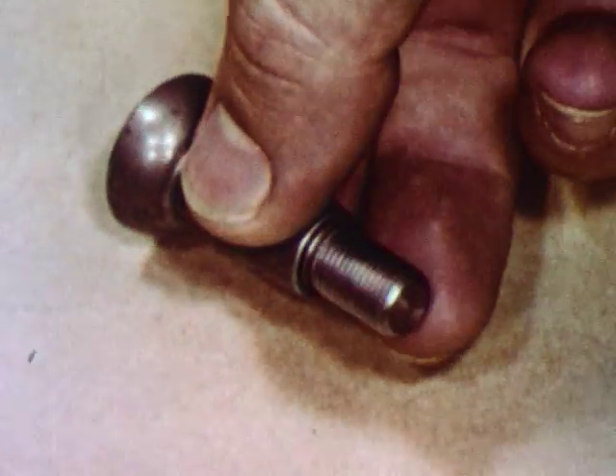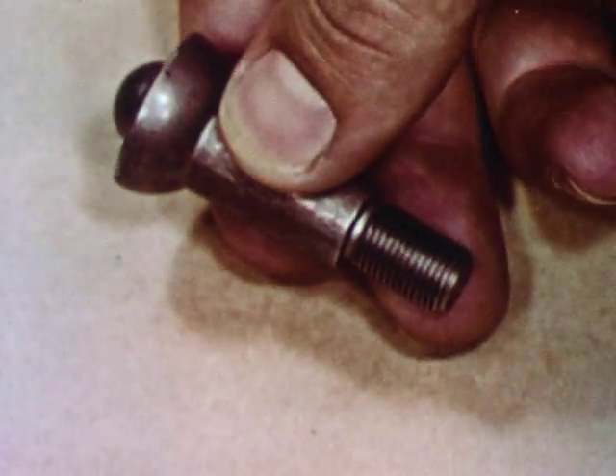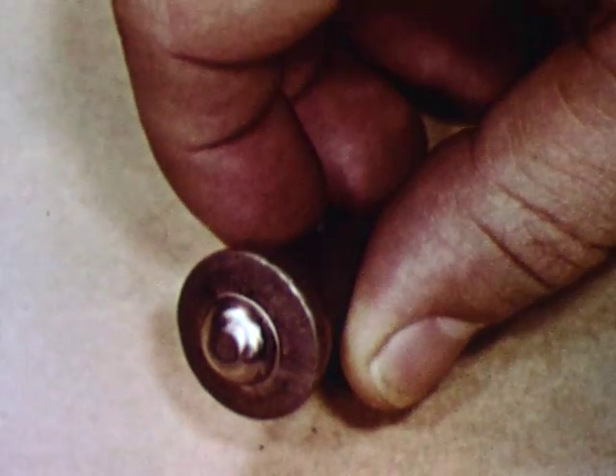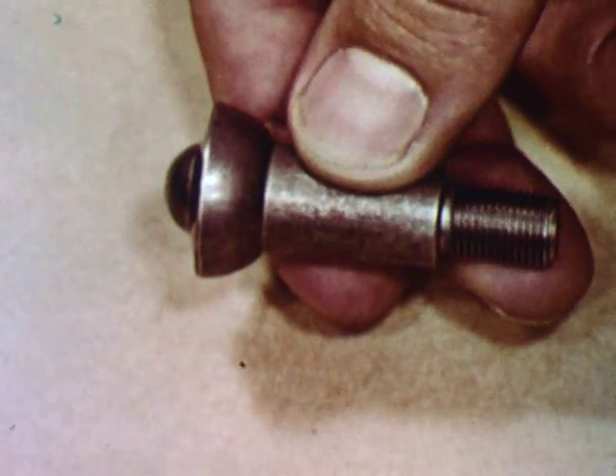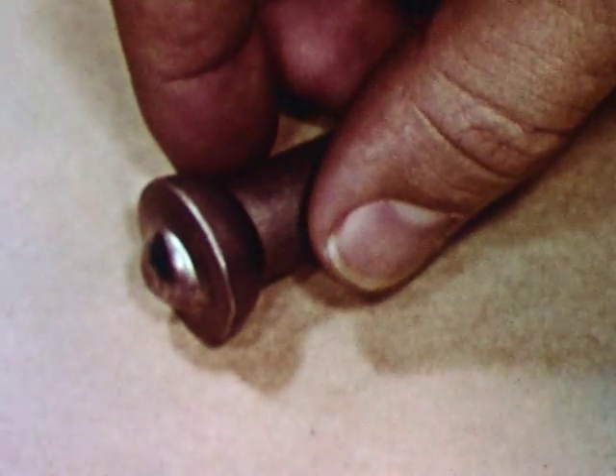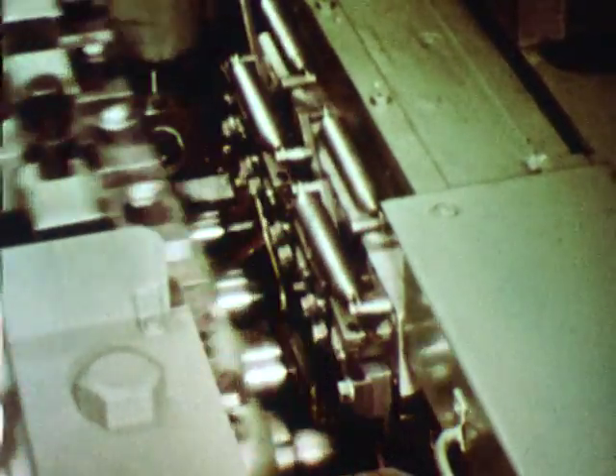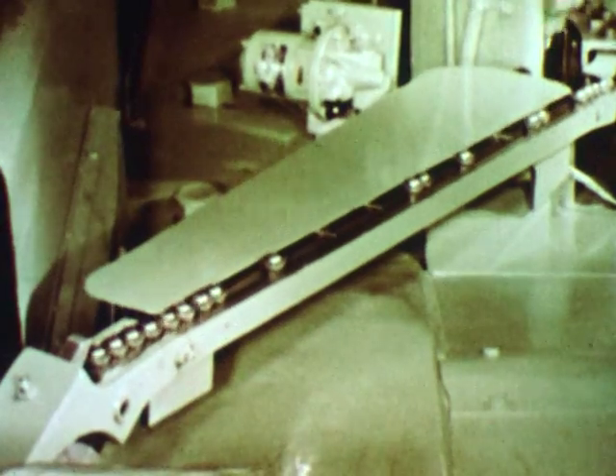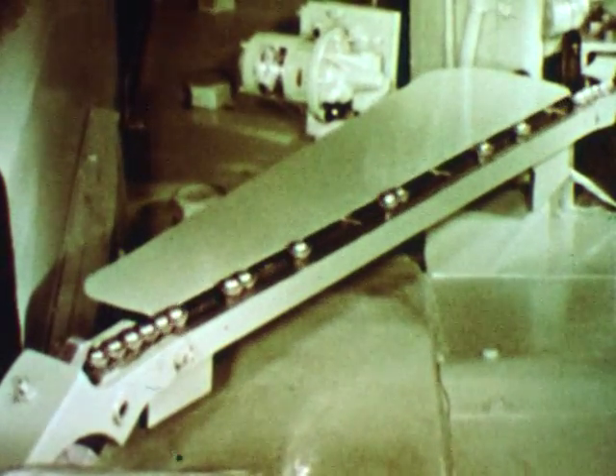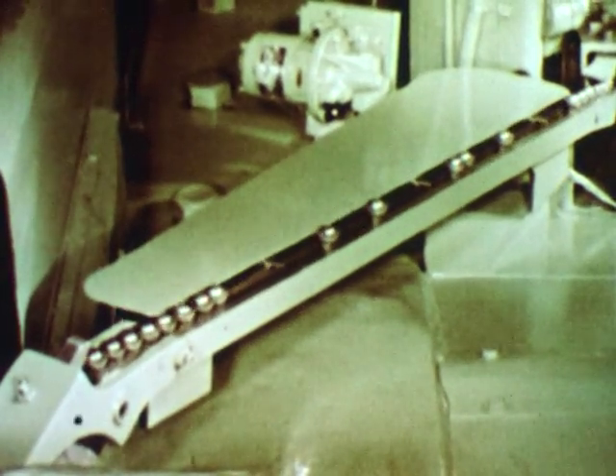This ball stud is produced on a 5/8 4-die bolt maker from 1038 steel wire at 60 per minute. The tapered shank and the sharp corner made this a challenging forming job. Following cutoff, the part is formed in 3 dies. It is blown up the pointer tube in the 5th station. An air-operated pointer chuck keeps the round-headed part from spinning with the cutters. Because of the unique shape of the head, we move the part up the tracks with a conveyor. Threads are rolled on the small end up to the shoulder.